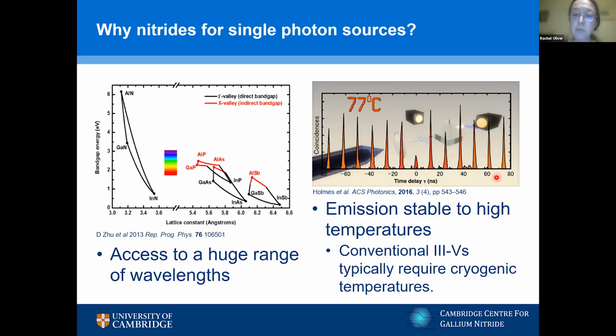This is from Mark Holmes' group. This is not my work, but it's a really lovely example of what the nitrides can achieve. And here we have a single photon emitter, which is operating at 77 degrees C. Note 77 Celsius, above 0, not 77 Kelvin. This is a temperature which would be hot enough to cook an egg. So this is really exciting in terms of potential real world applications and not having to use liquid cryogens to do this type of experiment and this type of technology.